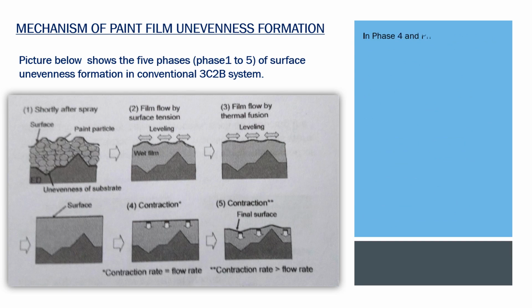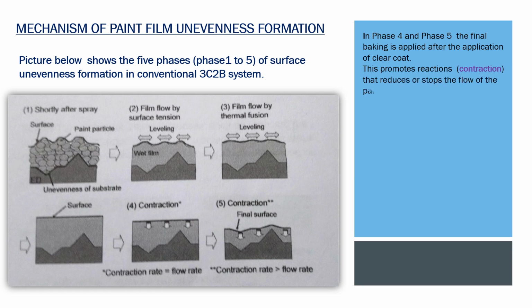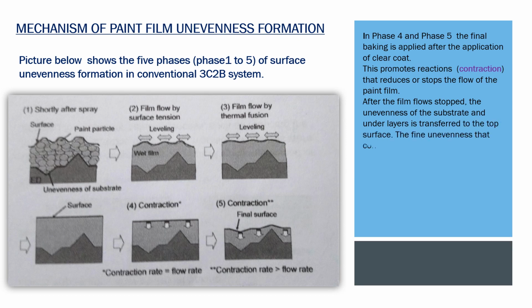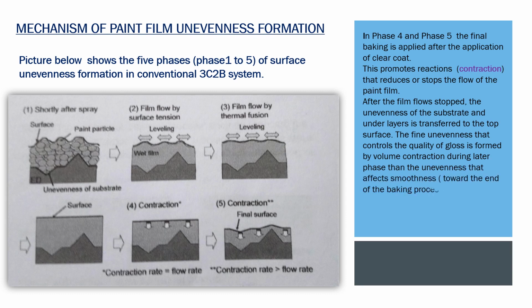Phase 4 and Phase 5. In these phases the final baking is applied after the application of clear coat. This promotes reactions and contraction that reduce or stop the flow of the paint film. After the film flow stops, the unevenness of the substrate and underlayers is transferred to the top surface. The fine unevenness that controls the quality of gloss is formed by volume contraction in a later phase than the unevenness that affects smoothness, toward the end of the baking process. The unevenness that forms in Phases 4 and 5 is mainly short wave, SW, and affects gloss.